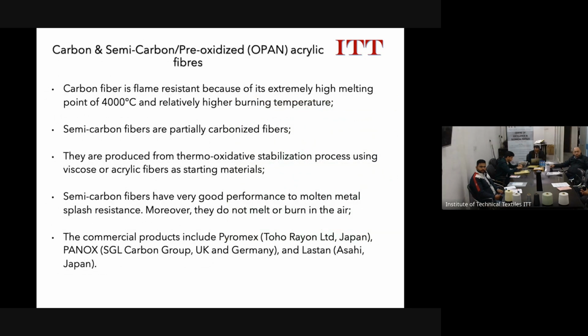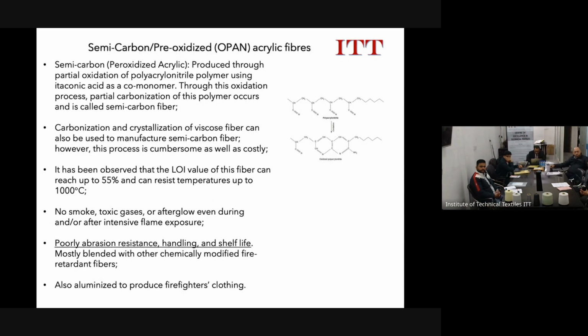Carbon and semi-carbon fibers, again, are not a new fiber. They're being used in India. A lot of companies are making products out of semi-carbon because these fibers are not very costly. You can get fibers or open fibers in the range of $5-6 a kg. But the challenge is converting it into yarn. This fiber is very brittle in nature. So the moment you put it in a carding machine, a lot of dust and powder starts generating, and a lot of contamination. So we try not to use this in a bigger proportion, but it's a very good fiber.